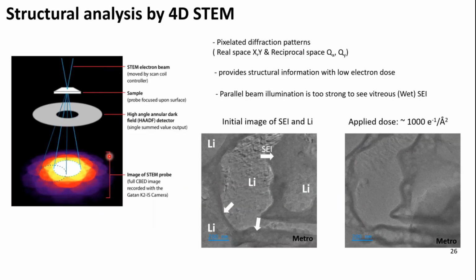We can also perform 4D STEM on the wet SEI to acquire structure information. From 4D STEM, you can get pixelated diffraction patterns in four dimensions: real space X, Y, and reciprocal space QX and QY. And this certainly provides structure information. And if you have a direct electron detector, we can have 4D data sets with low electron dose. The motivation of using 4D STEM is that parallel beam illumination has too much electron beam dose, and it can damage vitrified electrolyte very easily.